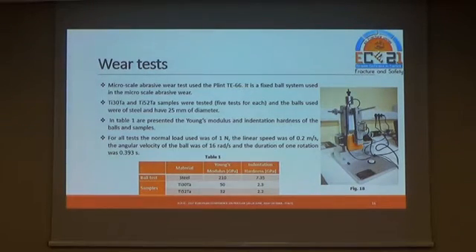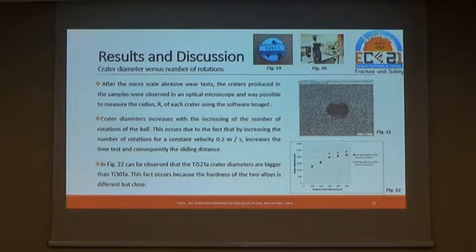For all tests, the normal load was 1 Newton. The linear speed was 0.2 meters per second. The angular velocity of the ball was 16 radians per second, and the duration of one rotation was 0.393 seconds. After the microscale abrasive wear test, the craters produced in the samples were observed in an optical microscope, and it was possible to measure the radius R.